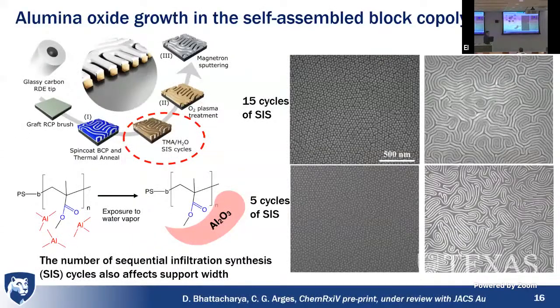So I want to tell you a little bit more about the sequential infiltration synthesis using an atomic layer deposition tool. This is where we grow the aluminum oxide in one of the polymer blocks. So we pass in trimethyl aluminum. This will coordinate with the ester group, this carbonyl group in the methyl methacrylate block. Then we'll purge the chamber, but that trimethyl aluminum will hang around. We pass water and we make aluminum oxide, and we'll do this multiple times. And the number of cycles we do in this process will dictate the width of this alumina structure within the